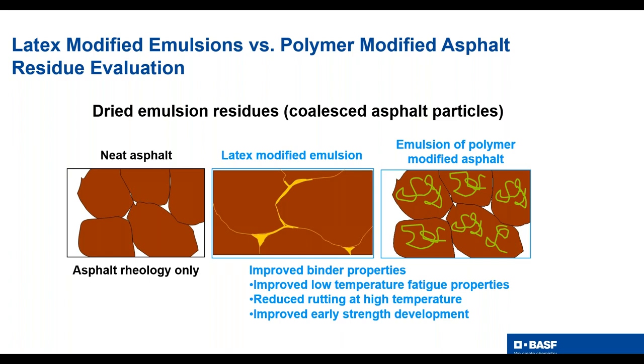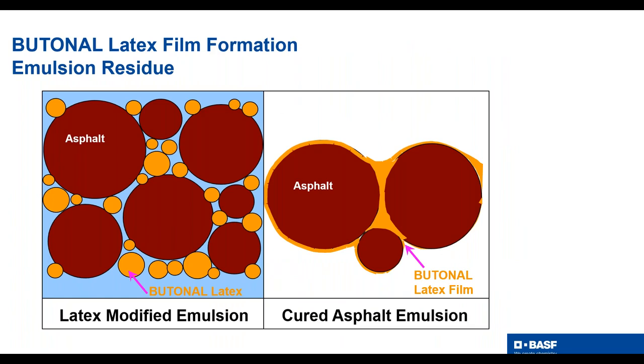And the softening points and things that polymer creates can make it a lot more difficult to get good cohesion results in microsurfacing and cooler temperatures with running a modified asphalt in a microsurfacing versus using a latex modified emulsion. But with both of them, polymers, you improve the binder properties and the properties that you want to see in the residual requirements, whether you're using an SBR or another polymer modified asphalt. Here's just a picture of an example of this latex and how it forms a film formation again on the product itself and the film around it. Again, I've got a good picture that I'll show you a little later that will really identify this from an actual mix in the field.